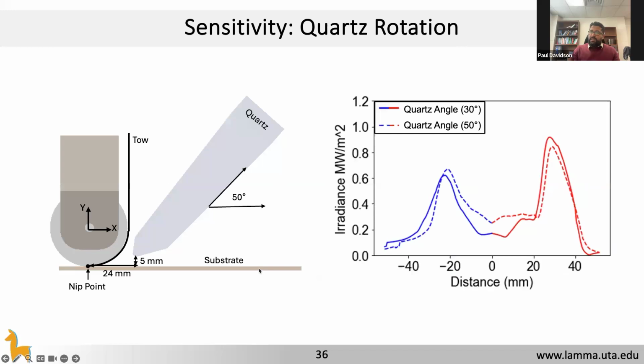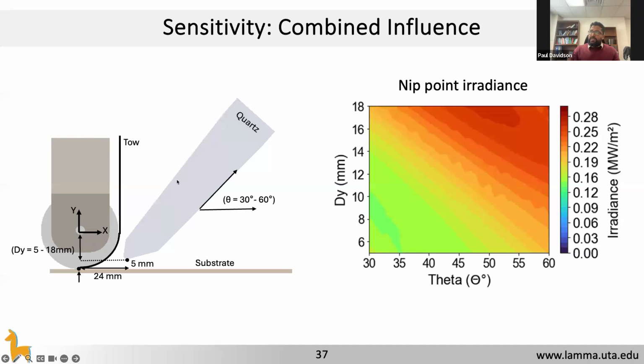Now, if you change the angle of the quartz, you can change the distribution of the energy as it's coming on the tape as well as the substrate. And then if you combine all the influences, we can look at how the geometric distribution changes the intensity of the flux itself. So this is the nip point irradiance. If you know the nip point irradiance, then we can calculate what the intensity of flux was at different locations within the tow and the tape.